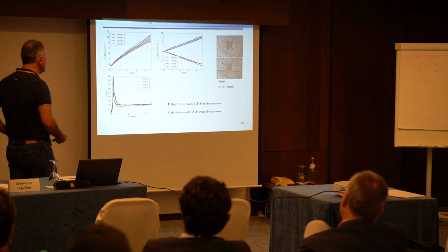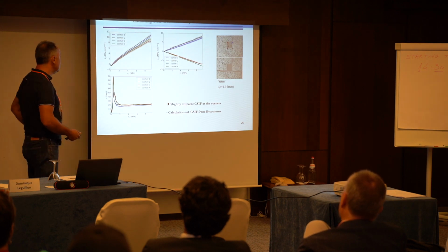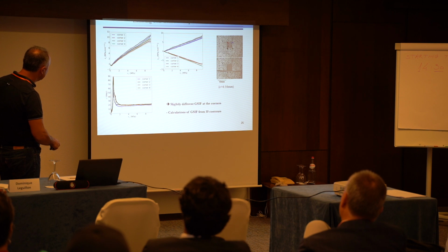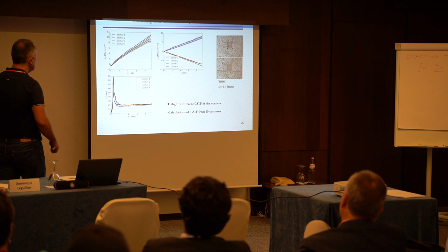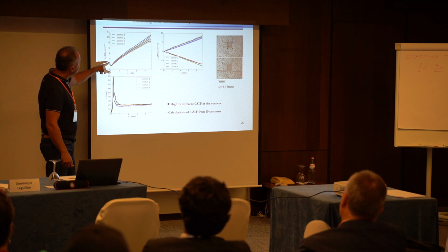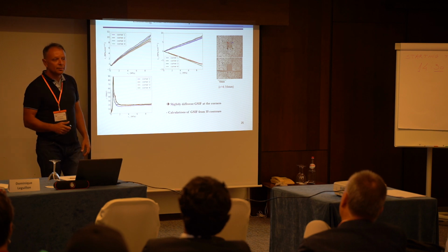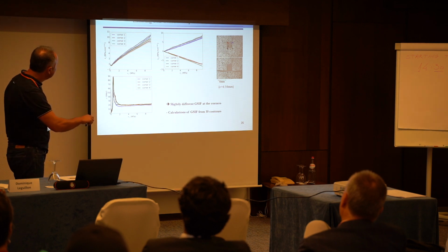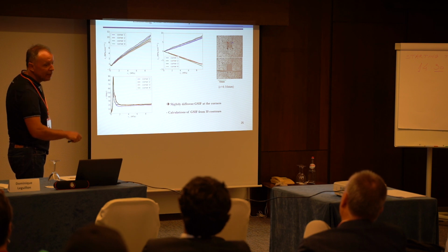Then what happens with DIC? What happens is shown here. Here it is the mode 1, here it is the mode 2, and here it is the calculation of the mode mixity. What do you see here? Black, blue, green, red correspond to the four columns. And a little bit of a gray thing that corresponds to what? The calculation on repeated and distinct path integrals around each notch.